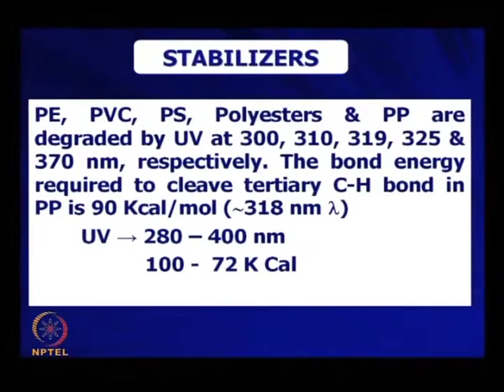Here you see why: this degradation wavelength is 370 nanometer, which is there in sunlight. So, it degrades. Polypropylene is not stable, and polyethylene is a little better, because polyethylene degrades at around 300 nanometer, which is a very small fraction in sunlight, but around 370 is present in sunlight. The bond energy required to cleave the tertiary carbon hydrogen bond in polypropylene is 90 kilocalories per mole, around 318 nanometer wavelength.